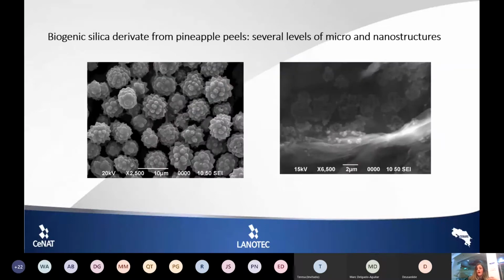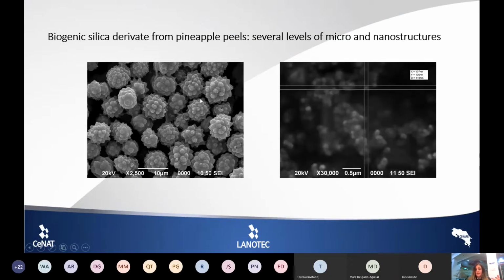So we can use this biogenic silica to make antimicrobial films, coatings from other materials for avoiding antimicrobial attachment or survival. So something really interesting that we learned in the process of analyzing the silica is that this is a microstructure that is formed by several nanostructures. There are several levels of building. It's not built in a single level. We could find at least two more levels. We can find plates, and also nanoparticles.